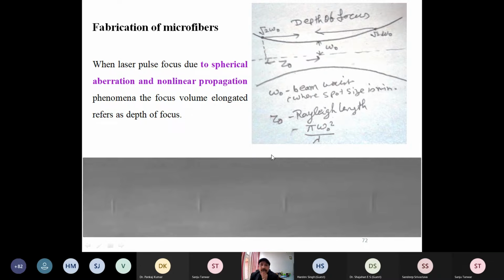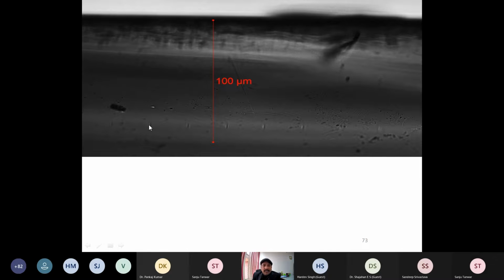You can make microfibers. But in making microfibers within a glass slide or any glass slab, the problem is that when the laser starts moving and focusing, some spherical aberration takes place, and due to nonlinear propagation, the end point is never circular. So you can see this is elongated in one particular dimension due to the depth of focus. We make these structures, and at the end you can see here.